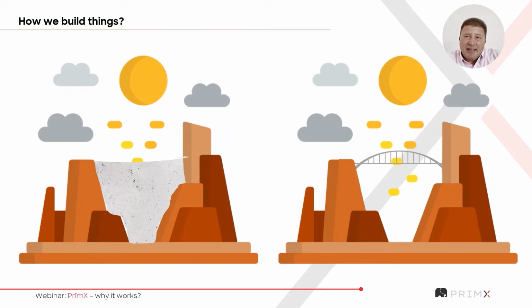is actually nothing more than a problem of shear, some microns away from the face of the steel, in fact in the steel and mortar interface. And what does that mean? Well, it means that if you look at a bridge of a significant gap and you look at the 12-metre long bars that are laid across that bridge, they're held together with nothing more than lap length. And if you look at them from far enough away, they look a little bit like very, very small things. In fact, they look a bit like fibres.